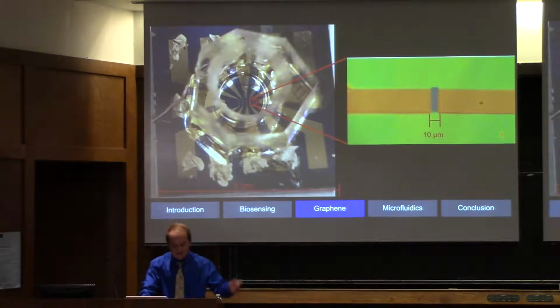The clear circle around the center of this device is actually a well that we made out of the polymer PDMS. We use this well to administer the different biomolecules. Basically, we just fill them up with the different biomolecules in solution and allow them to sit on top of the graphene so that they can bond.